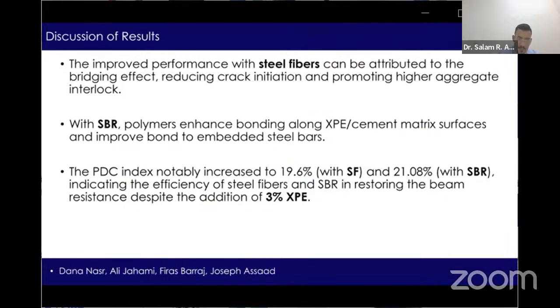So for the case of concrete containing steel fibers, the improvement in performance can be due to the bridging effect that reduces the initiation of cracks during loading and promotes higher aggregate interlock along the cracks. Alternatively, for the case of concrete containing SBR, the improved performance can be due to the presence of polymers that enhance the bonding along the XPE particles and cement matrix surfaces. Additionally, the use of SBR improved the bond to embedded steel bars, which densifies the interfaces along the longitudinal reinforcement.